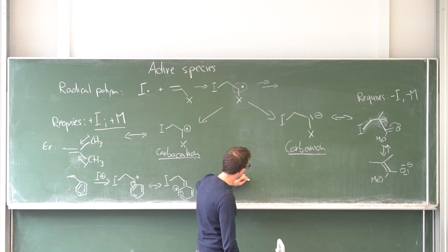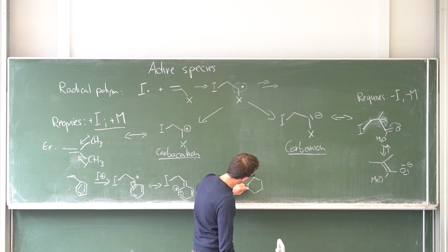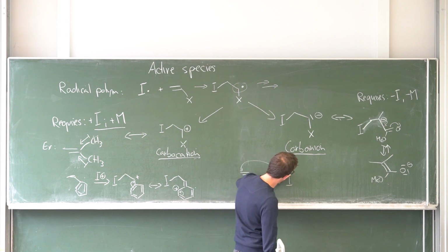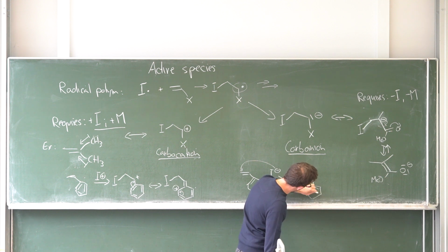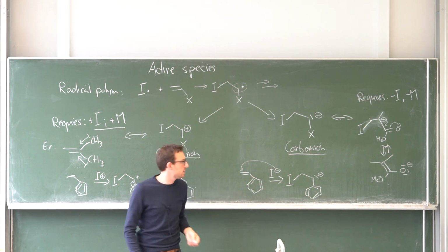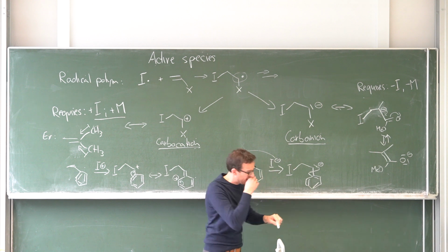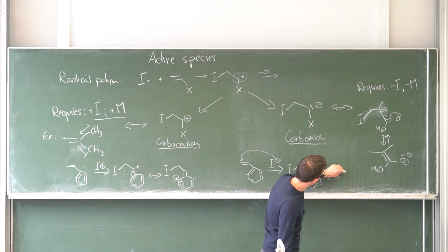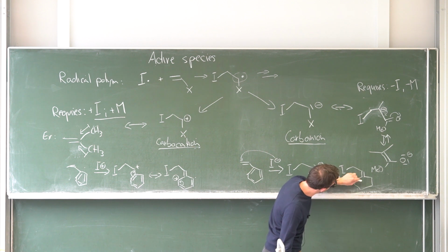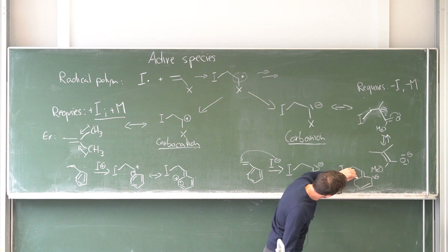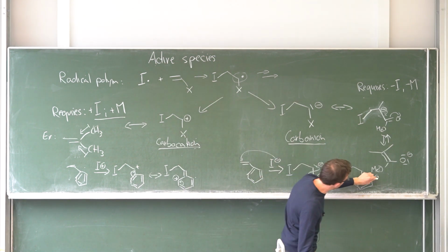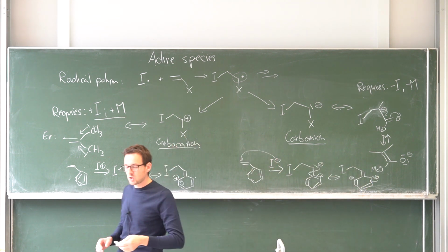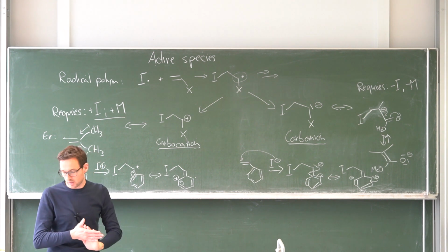And similarly, if we have a negative initiator, then this can attack here and we will form a carbanion. In this case, now the electrons can go into this bond connecting the ring, and this will make space here. So as a mesomeric stabilization, we get a scenario where now the negative charge is within the ring, and within the ring, again, it can propagate here and here as well. So the negative charge as well as the positive charge can be distributed throughout this aromatic ring.